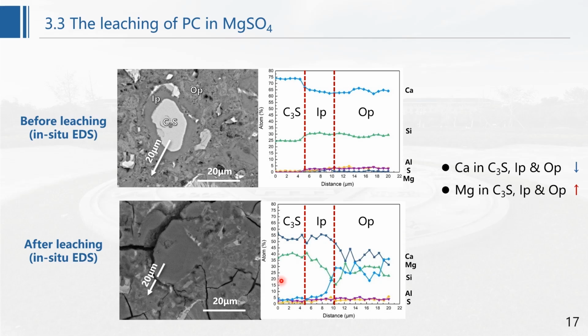Here are EDS results of PC paste before and after leaching in magnesium sulfate. We can see that after leaching, the calcium in C3S inner product and outer product all decrease significantly, which is more obvious than the previous groups, while the relative content of magnesium in C3S inner product and outer product increased significantly.